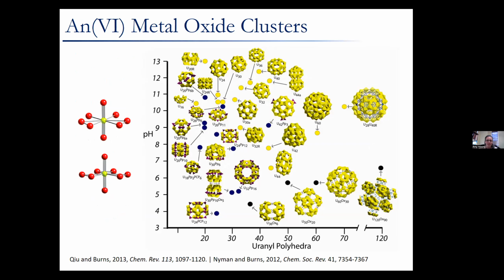If you're not familiar with looking at structures in this way, each of those yellow polyhedra has a uranium metal center at the middle, and all of the vertices represent, in this case, oxygen atoms that are bonded. So these are an example of clusters where we also have oxo oxygens that are terminating the surface of the nanoclusters. And then we have linkages in the equatorial plane, either as peroxide or hydroxide, to form these hollow spherical structures. You'll see there's also a diversity in the structures themselves.